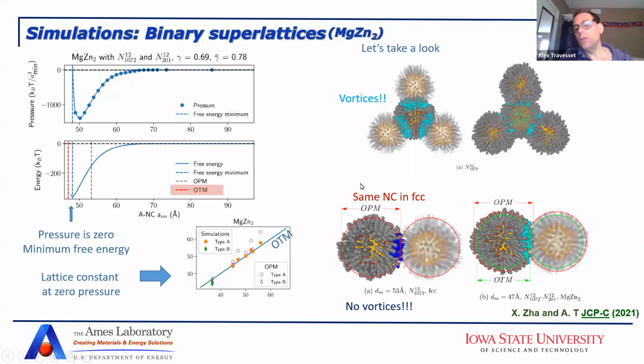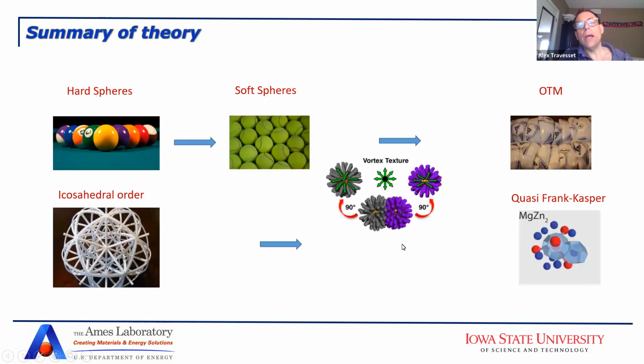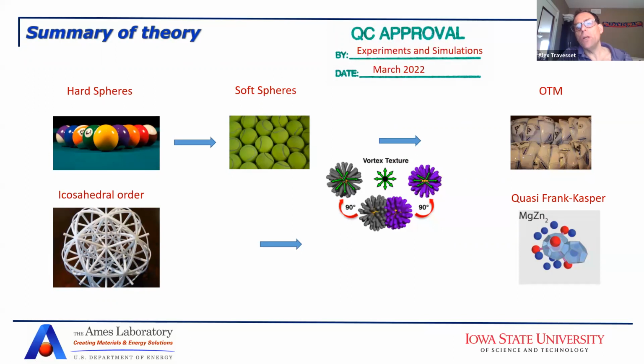And this is true for magnesium zinc 2, but it is also true for all the binary superlattices that we've looked at. And we've looked at quite a few. In this paper, you can find all the details. So I've been able to show you a summary of the theory that we started with hard spheres. We went to soft spheres. That didn't really help that much. But in the end, what helped is the OTM, the icosahedral order, and the quasi-Frank-Kasper phases. I've done extensive comparisons with experiments and simulations, and as of March 2022, the theory is as good as it gets. We haven't had a single case of a discrepancy with this theory.